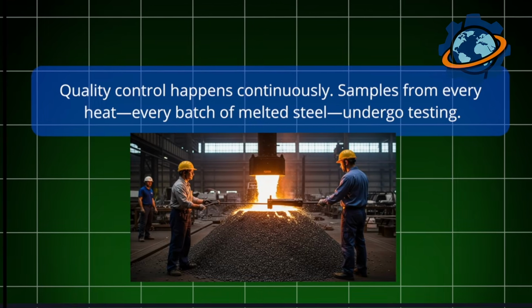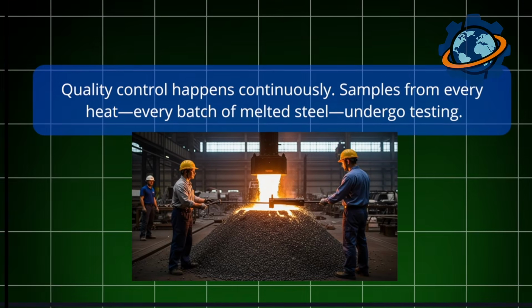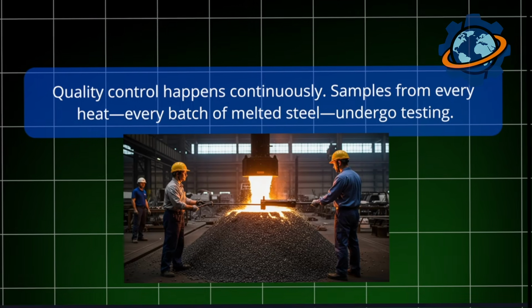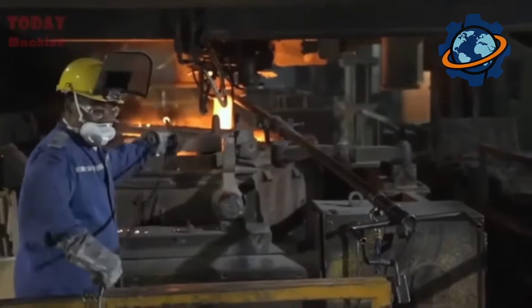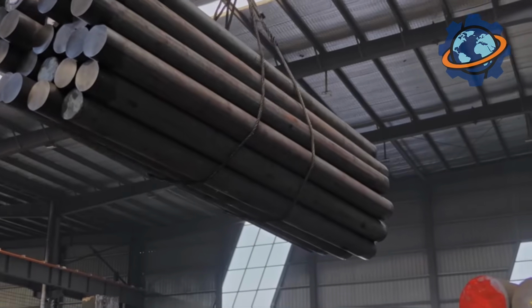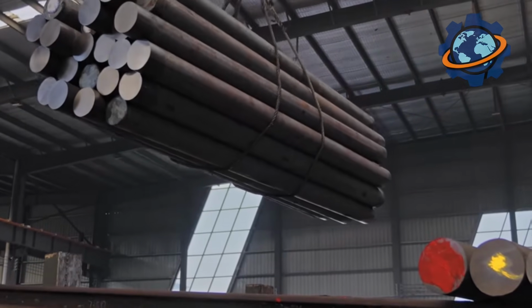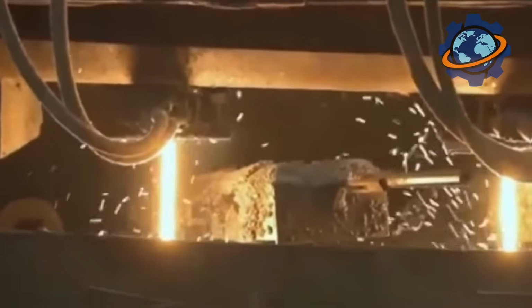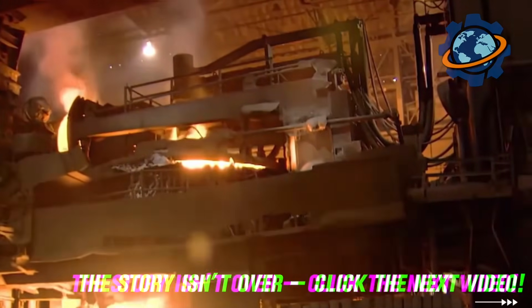Quality control happens continuously. Samples from every heat, every batch of melted steel, undergo testing. Tensile machines pull specimens until they break, measuring yield strength, ultimate strength, elongation. Chemical analysis verifies carbon, manganese, silicon content. Dimensional inspection confirms rib height, spacing, and bar diameter. Every bar carries traceability, heat number linking it to specific melt, specific chemistry, specific mechanical properties.